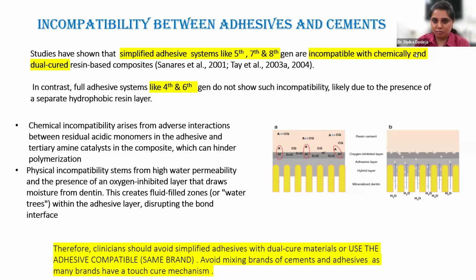And so this system will act as a hydrophilic layer, as in it will let the moisture remain on its surface, because they have that hydrophilic component to it. So that moisture will also lead to bonding issues. Also, the residual acidic monomers in the adhesive will combine with the tertiary amines in the composite, which can hinder polymerization. So as you all can see in the image, the free hydrogen from the adhesive, from the bonding agent, reacts with the tertiary amine which is present in the cement. Okay. So this reaction will also hinder the polymerization.